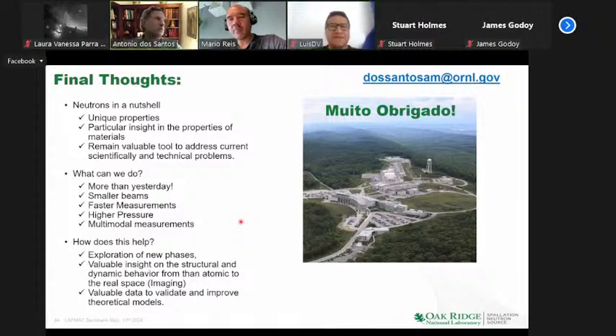All right. Thank you for your question, Luis. Now, there's a lot to unpack there. So we do have many magnets. Now, of course, diffraction is not really a transmission because you're confined by Bragg's law to some scattering angle. Now, we do have magnets, I believe at 5 Tesla, for small angle neutron scattering. So you can go in transmission and say, in your case, because from your question I understand, you can say like skyrmions, and they have been studied with SANS to see large magnetic structures. Sorry, I meant skyrmions, not magnetic vortices. Well, those two. But if you have really long range magnetic structures, you can study with SANS up to 5 Tesla. Most magnets are compatible with a helium-3 stick, so you can go to at least hundreds of millikelvin, certainly below 1 Kelvin on all the magnets.